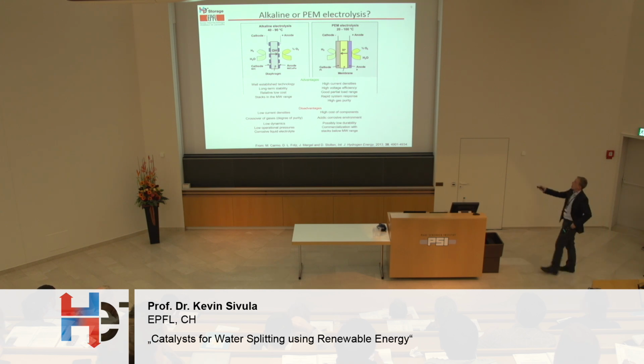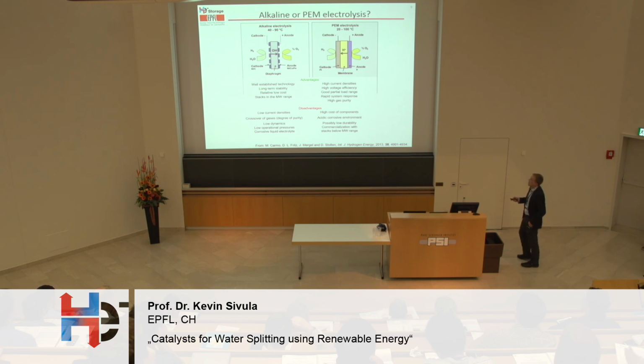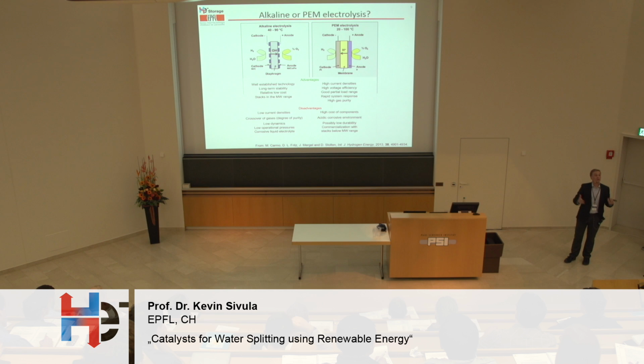Of course, alkaline electrolysis is well established. It can be very stable in the long term, and it's relatively low cost. However, it doesn't work very well in a dynamic environment. In fact, they work the best if we can keep the current density the same and relatively high on these electrolyzers at all times. In fact, if we turn these things off and just let them sit in the caustic bath of the electrolyte, those electrodes are going to corrode. That's a big drawback for this type of technology.